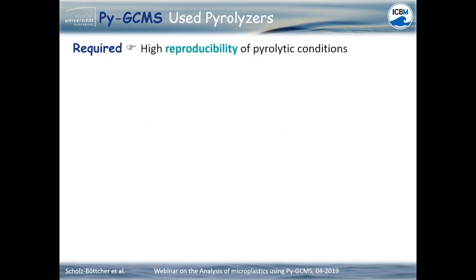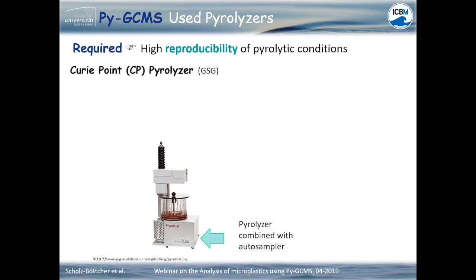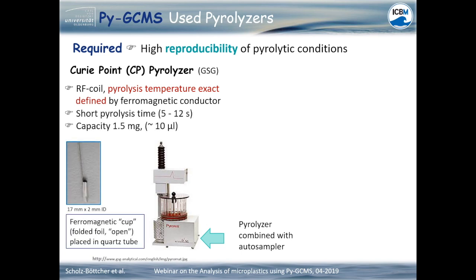Quantification with pyrolysis requires a very high reproducibility of pyrolytic conditions. In our first studies, we used the Curie-point pyrolyzer that enables a very precise and reproducible pyrolysis temperature due to a defined ferromagnetic conductor. And it has very short pyrolysis times. The capacity as well as the dimensions of the pyrolytic cups are quite small.